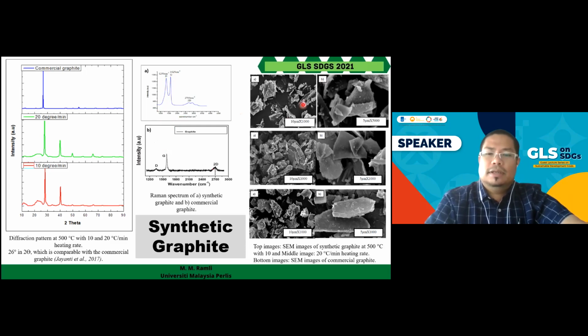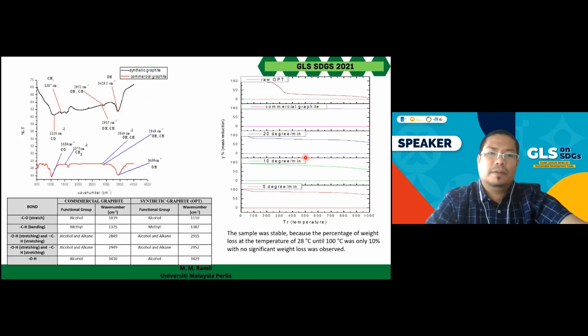And then we did some scanning electron microscopy images, and here are the images for the commercial graphite, and these two are basically the images for our synthetic graphite at 500 degrees C with 10 degrees C per minute and 20 degrees C per minute. Okay, and then we did further characterization, this time with the FTIR, where we wanted to see the comparison between the commercial graphite and the synthetic graphite in terms of the functional groups there. Okay.